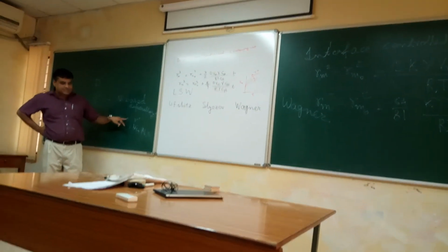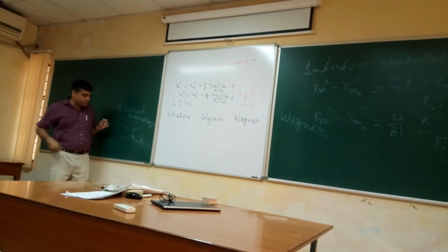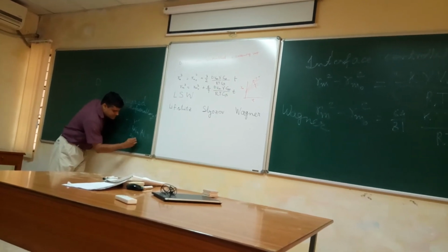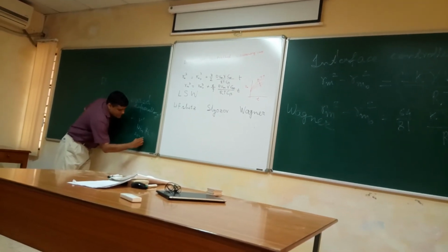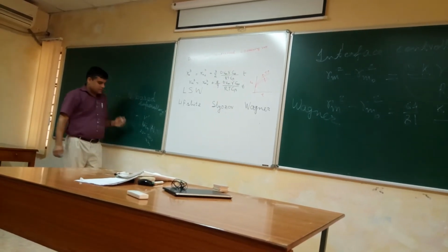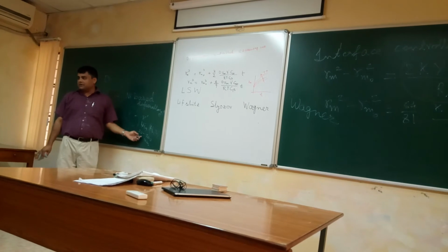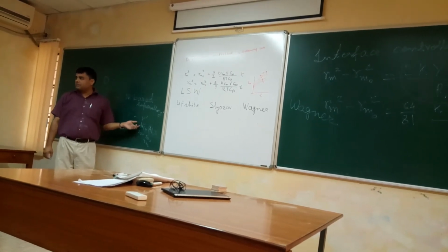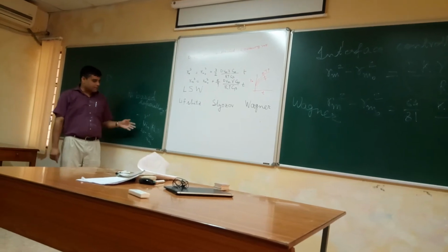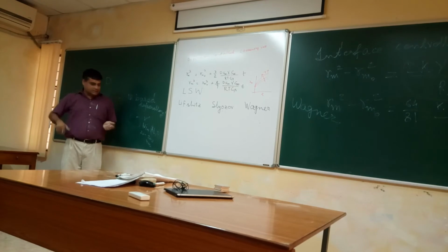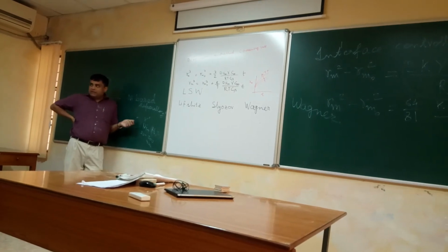These gamma prime sizes are around 20 to 200 nanometer. Usually it is less than 100 nanometer, 40-50 nanometer size gamma prime. Gamma prime can be either spheroidal or cuboidal; precipitate shape may differ.